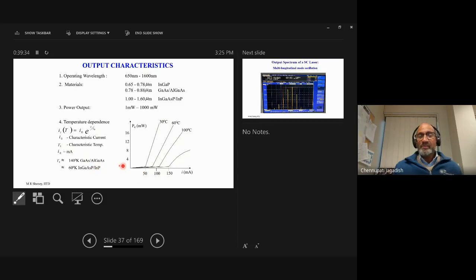You can see the gallium arsenide, aluminum gallium arsenide has a higher characteristic temperature than indium phosphide, indium gallium arsenide phosphide, because of the so-called band discontinuities between the smaller band gap material and the larger band gap material. Those band discontinuities are smaller in the case of indium phosphide structures than gallium arsenide. So that's why you end up having higher T naught, for example. That means these lasers operating from the gallium arsenide structures will be much more thermally stable than the indium phosphide ones.